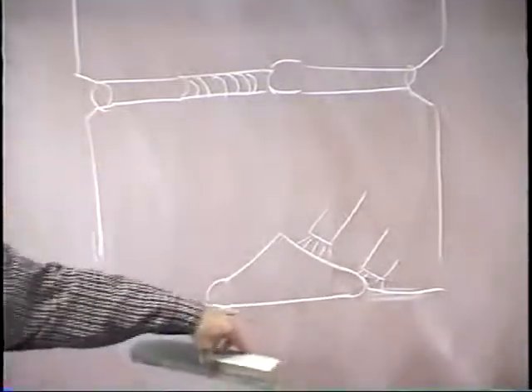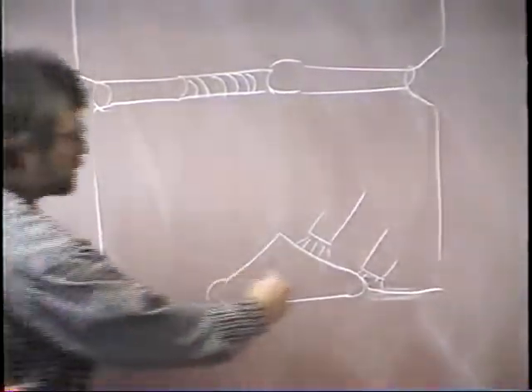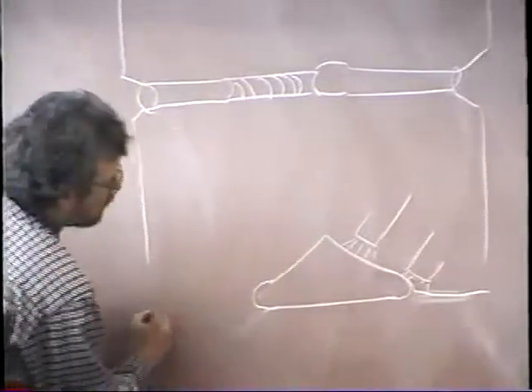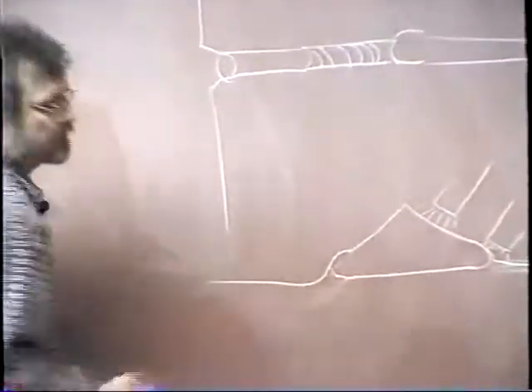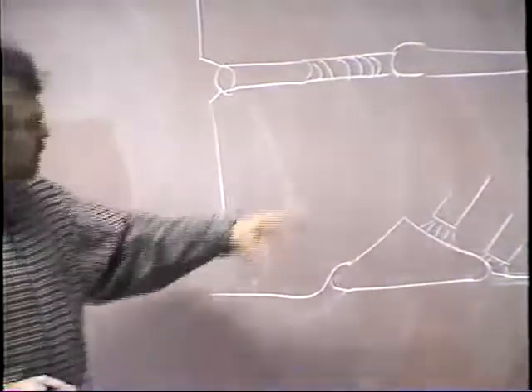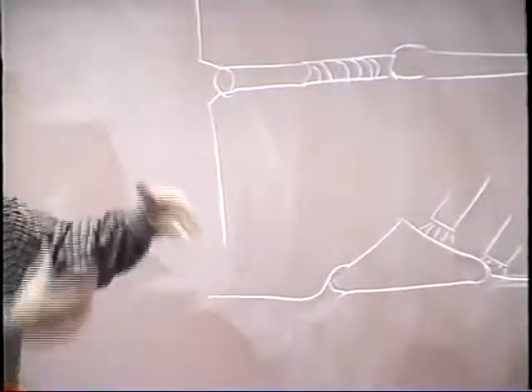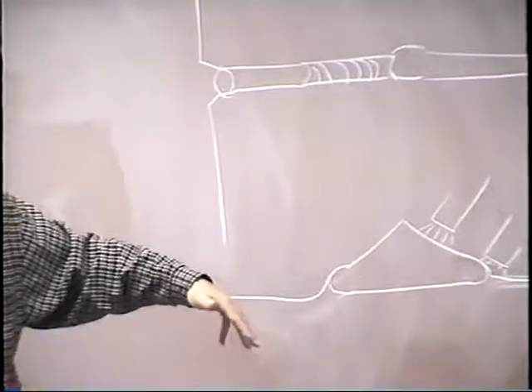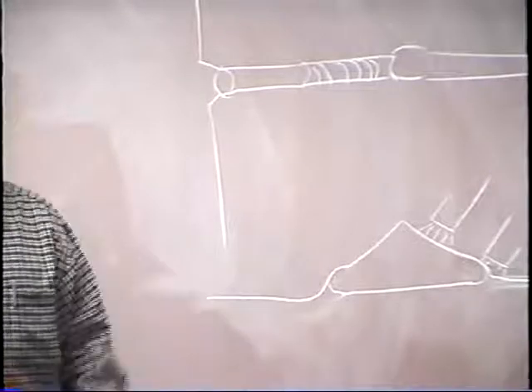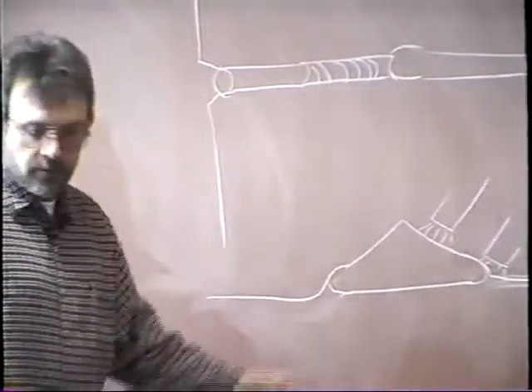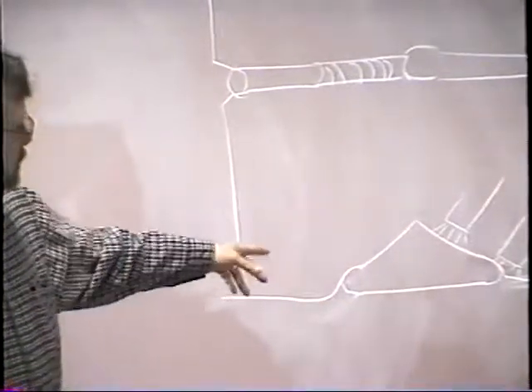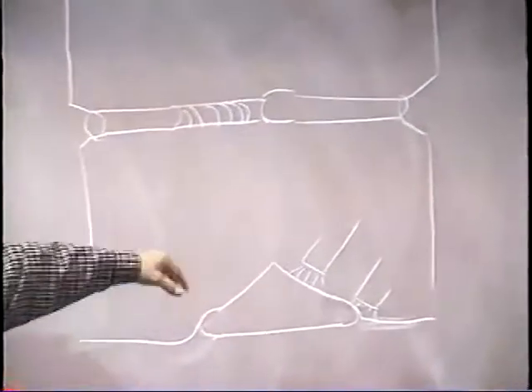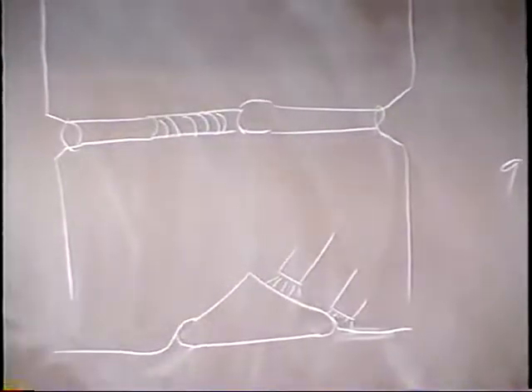These are called toenails, and you'll get them going out of a tack, and you'll get them coming into a tack. Toenails. So the best solution for those is to go ahead and feather those tacks properly, and then come out slowly, burn through the tack before you reach the end. You get a good tie-in. But coming into a tack now is, in my view, tougher than going out of a tack.